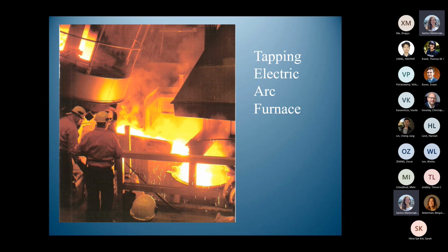But of course, it's manufacturing inclusions like there's no tomorrow. Okay? So the steel in the furnace, this is a little arc furnace here. It's about a 5-ton arc furnace by the look of it. The steel in the furnace would have been really quite good because it sits in there for some time while it's treated and you get the composition right and the carbon out and whatever. So it's been in there for about an hour or so, during which time, in this very shallow bath, there's plenty of time for nearly all the inclusions to float out. So your steel's in really quite good condition in the furnace. And then, horror of horrors, you tilt the whole furnace, it all thunders out into a ladle at least 3 meters down in a pit and completely destroys all that good quality.